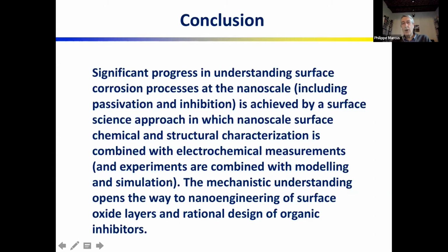And the reason is that the experiments we are doing, being at the nanometric or atomic or molecular scale, can be directly translated in DFT. And that's very important because it may be shown later, but it is very important because when you choose the model in DFT, you need to have experimental results to choose the right model. And as our experiments are done at the same level in terms of dimensions as DFT, we can use the measurements to start with the right DFT model.